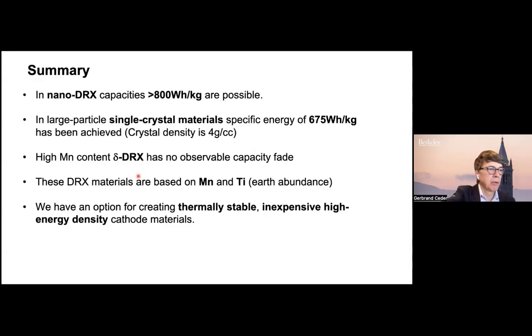So with that, I'll summarize so we can have some discussion. One takeaway is that DRX is a whole family, so don't get confused. There have been nickel-based, vanadium-based, and chromium-based DRXs. In the heavily milled powders, we've certainly seen capacities well over 800 watt hours per kilogram, even up to 1,000. In the more practical materials, the larger single crystal materials, the best number we've seen is 675 to 700. And of course, with a crystal density of 4 grams per cc, you're better than LFP on crystal density.